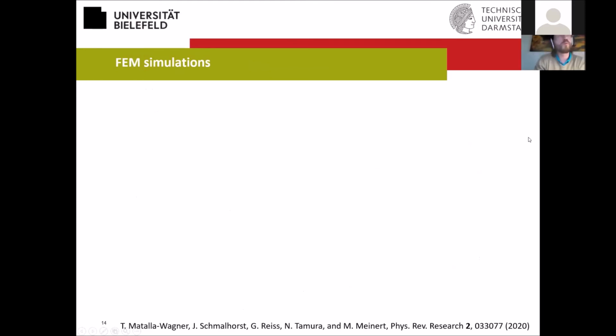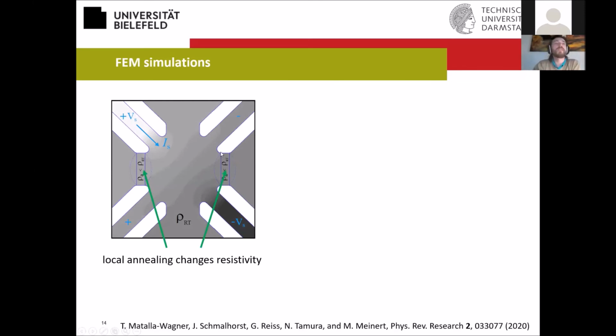Okay, so now we did some finite element simulations to understand this quantitatively. This is our model for the FEM simulation. We model this whole structure as having a constant resistivity, with the exception of these narrows here, where we look at either higher or lower resistivity. In this case, we model this with a lower resistivity to model this annealing effect. And we see that this leads to a transverse voltage drop when we pass a current through this probe line.